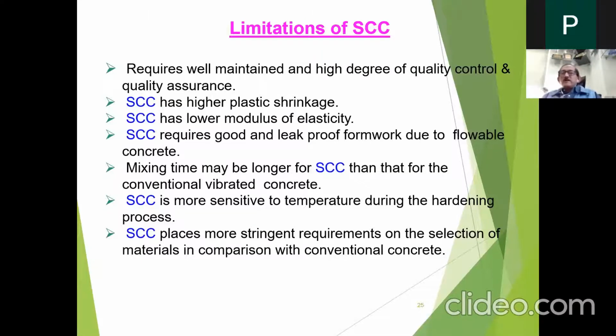Why? Because it has more paste. So because the paste content is more, it will have higher plastic shrinkage. It will have somewhat lower modulus of elasticity because the paste content is more, and the aggregate size has to be reduced, and the percentage of coarser aggregate is also to be reduced. Then SCC requires good and leak-proof formwork due to flowable concrete. It's like filling water or filling a liquid inside the pot. So the pot has to be leak-proof, otherwise everything will flow away.